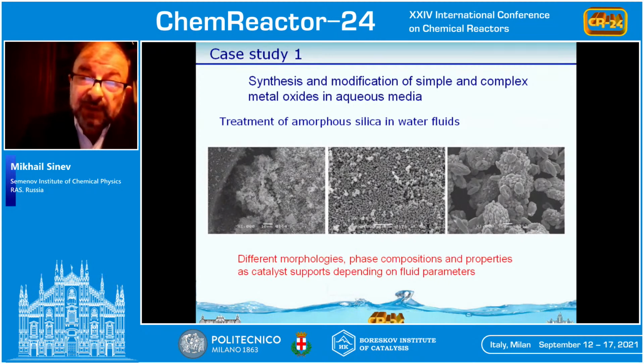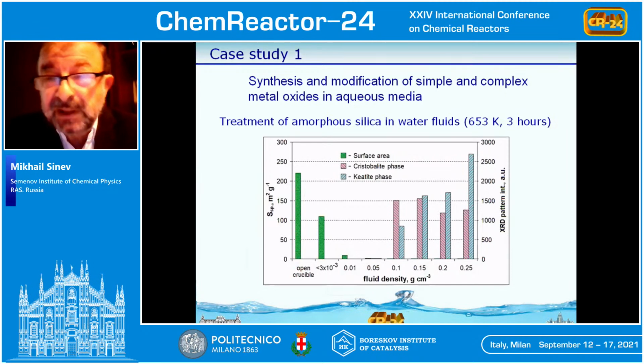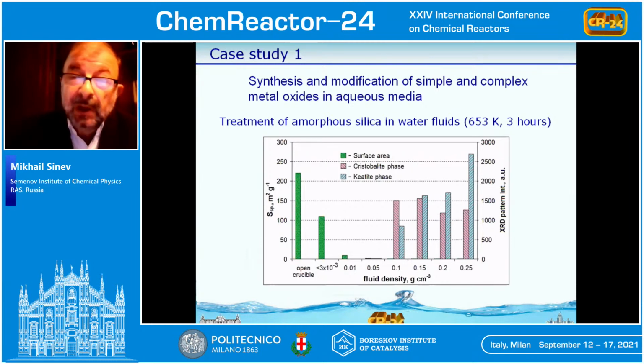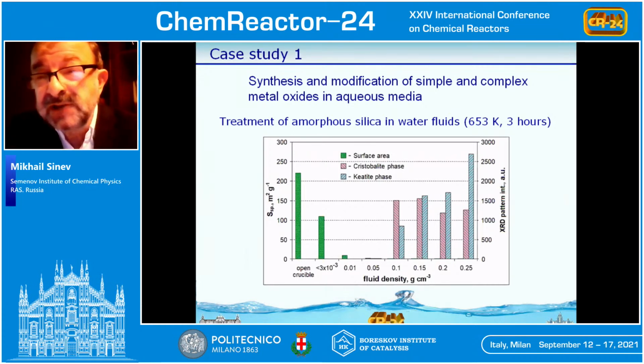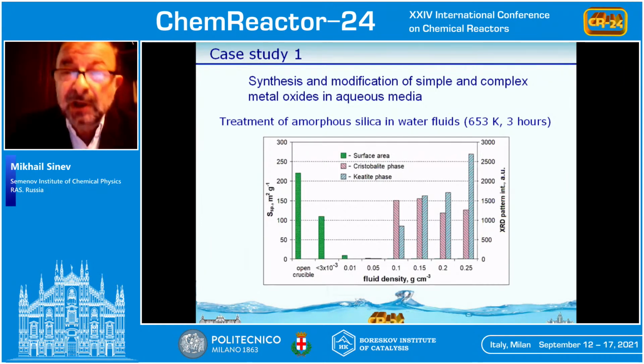And if we look at the dependence of the properties of the product on the parameters of the water fluid, we can see that we can vary a very simple parameter like density, because we can vary it by changing the amount of water which we load into the autoclave. At constant temperature, we can produce products with different surface areas, different phase compositions, and sometimes we are able to obtain very clean products in terms of morphology and phase compositions, and which are not, like, for instance, cristobalite in this case, which is a high temperature phase, but we can obtain it at relatively low temperature by using appropriate parameters of the water fluid.